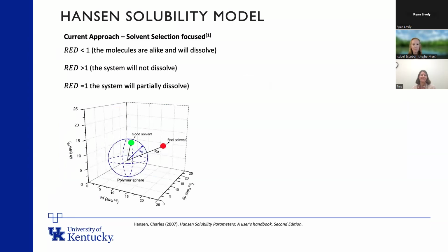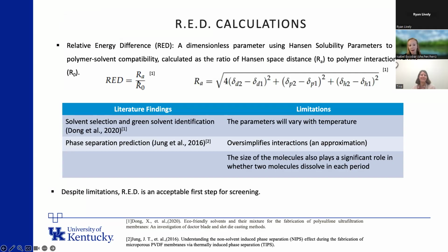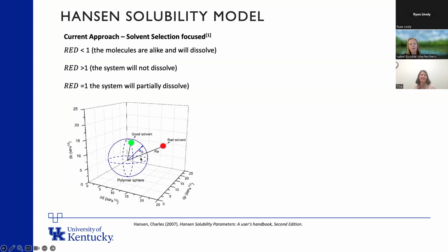The assumption is made for RED that the polymer is this perfect sphere. And in this perfect sphere, a good solvent with a relative energy difference less than 1 is one that, right here, can penetrate this perfect sphere. A bad solvent is one that cannot penetrate. So when we do the relative energy difference, which is the Ra divided by the R0, with the Ra being the Hansen solubility distance to the polymer interaction, as shown here, we see that if that ratio is greater than 1, there is no way that solvent could ever enter that sphere. And so it is considered an incompatible solvent for that polymer.